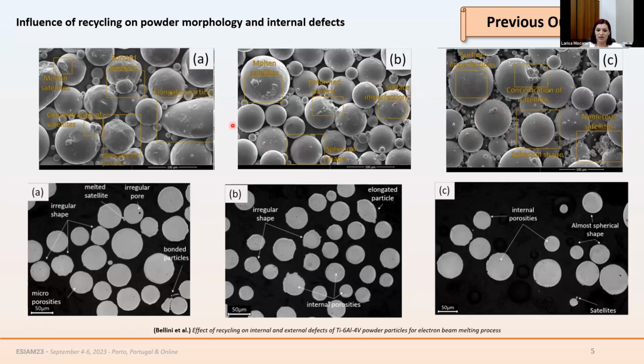Regarding the recycled powder, type B, we have an intermediate situation, while for type A, which is the powder recycled more than 100 times, we have a clear degradation of the particles. We have irregular shapes and also tiny particles bonded on the surface of the larger ones, some elongated particles, some broken particles, and so on. So we have a clear degradation with increasing recycling numbers of the powders.